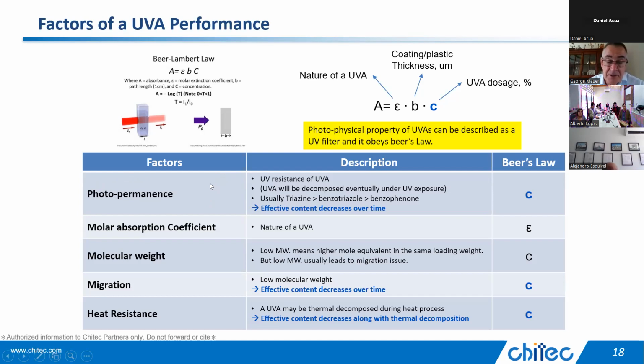Well, benzotriazoles and triazines are both pretty stable. Although if you go to a benzophenone or an oxalanilide or a cyanoacrylate, those are not photopermanent. And so they'll go away, and then they will not be contributing to your absorbance. The molar absorptivity coefficient is just how much light that UV absorber can absorb. And really, this coefficient should be looked at over different wavelengths. If you want to cover a broad spectrum, you would use a benzotriazole. Benzotriazole goes all the way out to 380 nanometers. If you go out to 380 nanometers, then you're covering really essentially the whole UV absorption spectrum, which is good. If you go beyond 380, then it's colored.